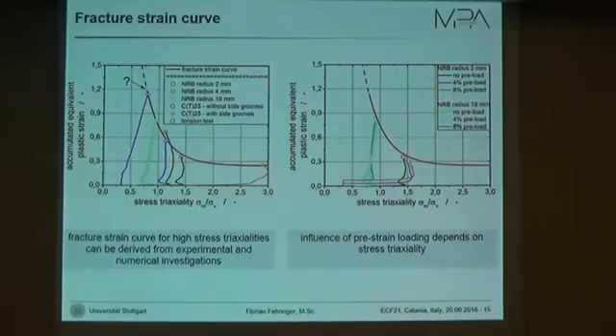We also took our results from the preloaded specimens to look into the influence of changing stress triaxiality on the limit strain. And you can see here the specimen with a 10 mm notch radius, which have a smaller stress triaxiality, and there's hardly any influence of the preload regarding the fracture strain. For the 2 mm notch radius specimen, with an increasing preload, with an increasing pre-strain, we have a reduction in the tolerable plastic strain and a slight increase in the stress triaxiality.